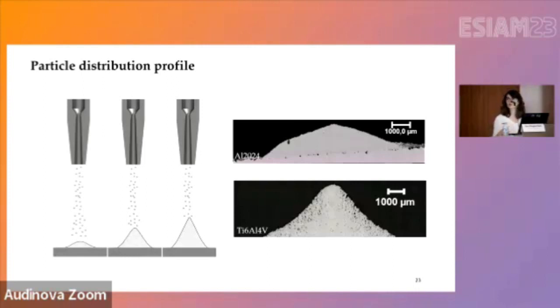The problem of the shape control for cold spray is that we are spraying using an axisymmetric commercially available nozzle. Because of the distribution of the particles in the flow, when using a low number of tracks or a high velocity for the nozzle transfer speed, we typically, not always, but typically get a Gaussian distribution. As we are increasing the number of tracks or decreasing the transfer speed of the nozzle, that would evolve into a triangular shape.